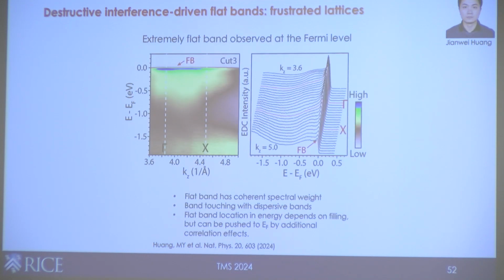Experimentally, what we saw is actually very striking, which is that you can see that there is this extremely flat band right at the Fermi level. If you don't see that very well with the color maps, what you can do is look at a bunch of the vertical energy distribution curves right here, and you can see that these sharp peaks are the flat band right at the Fermi level. We actually imaged these, and we have additional data that shows that this thing is flat in all three directions, Kx, Ky, and Kz.